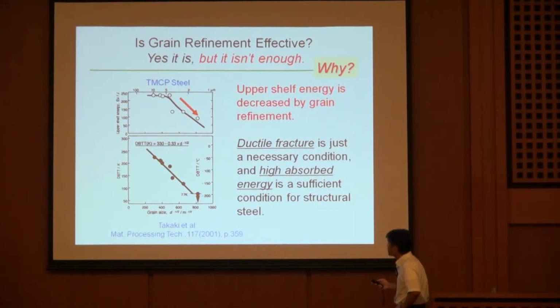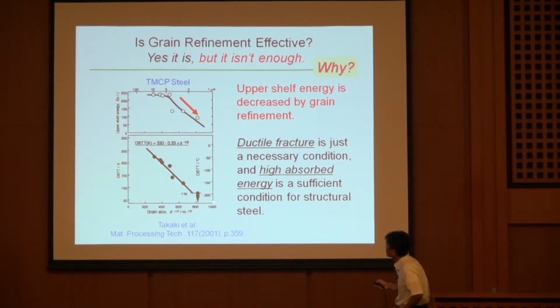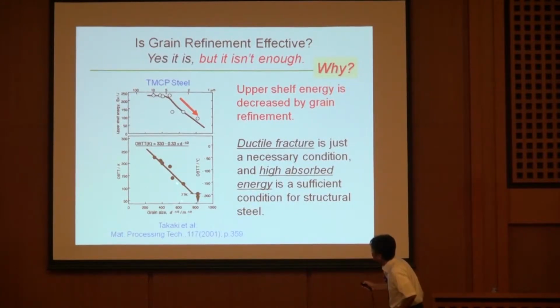So what this figure tells you is the ductile-brittle transition temperature versus the grain size. Grain size is finer on the right. Professor Takaki did some thermomechanical controlled processing on low-alloy steel. Then the ductile-brittle transition temperature decreases like this. So above this line, your steel behaves ductile, but below this, the material shows brittle fracture mode. So then you can get a safer material when the grain refinement has been done.